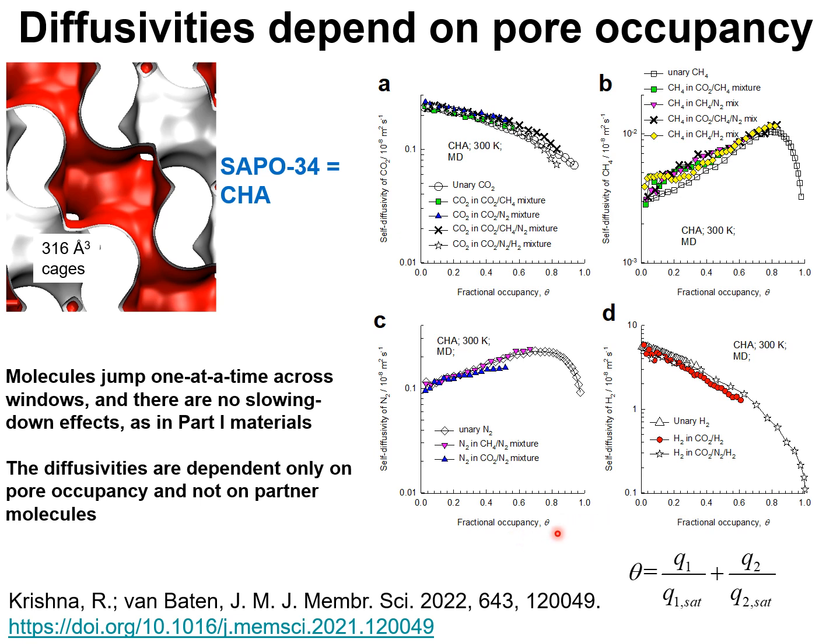provided we make the comparison at the same pore occupancy, and therefore the component permeance in the mixture is only dictated by mixture adsorption, and we can use the unary diffusivity data to describe mixture permeation.